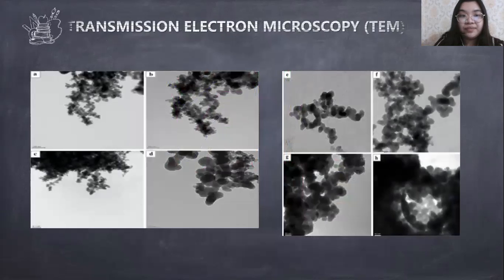On the other hand, figure 2 shows the TEM image of the silica oxide by vermicomposting. We can see in the picture how clustered they were. In this part, the G to H, the silica oxide particles were obtained from agro-industrial waste without biotransformation, and that is why they have elliptical particles with different diameters, and some have bigger size than the particles we can see on the left side. Thus, it means that bioprocessing is needed in order to reduce the size of the particles.